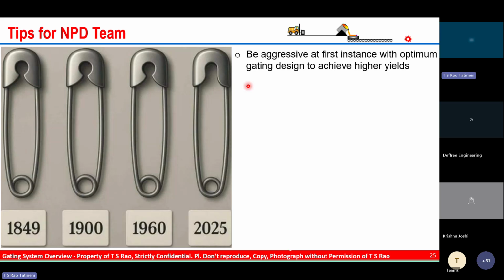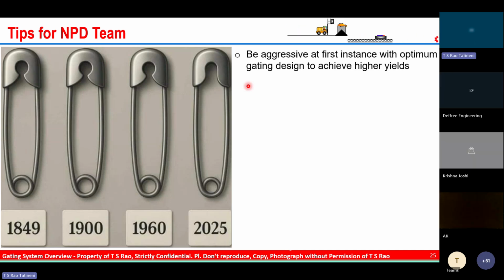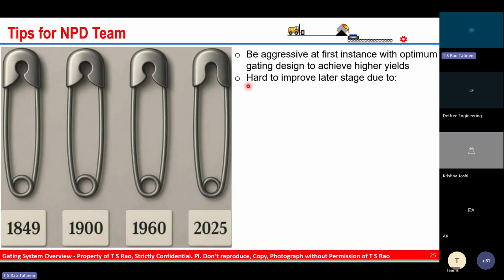Always we have to be aggressive in the first instance with an optimum gating design. Any product being developed for the first time, we have to be very, very aggressive. Always we have to achieve as high a yield as possible. If we can achieve 80%, 85%, we need to try the best and most aggressive gating design in the first instance. Some conventional foundries think, let us produce a sound casting first, and later we can improve as part of continual improvement, but it is very hard to implement because of various reasons. The first one is the fear of failure. Suppose you produce a sound casting without thinking of yield,